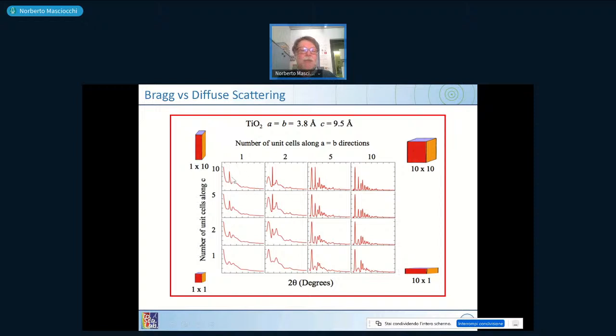Note that the peak which was emerging up here in the 1 by 10 system is missing here, because we are not elongating along C, but we are elongating along AB. So that means that if you have one of these patterns, you can easily distinguish the size and shape of your system. So the size and shape of your single crystal, once you get a sample of single crystal in a powder, can be easily retrieved by this plot.